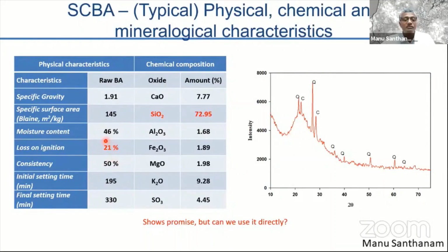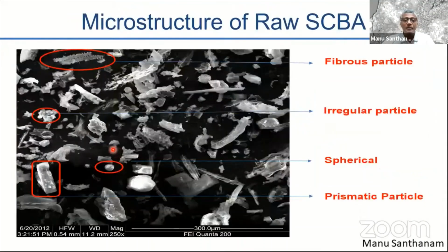The problem here is, of course, it's got a loss on ignition that is extremely high. So can we use it directly? The answer is no. If you want to use it as a cementitious material, you need to process it. So if you really look at the microstructure, you can see all kinds of stuff in this bagasse ash. What we want are these irregular shaped silica particles. But we also have these prismatic particles of silica, presumably those which are crystalline. And we also have these fibrous particles which are of the remnant carbon from the bagasse that has remained behind.